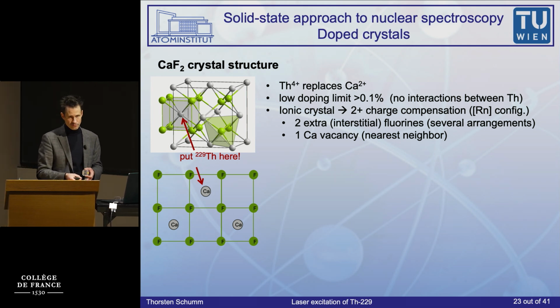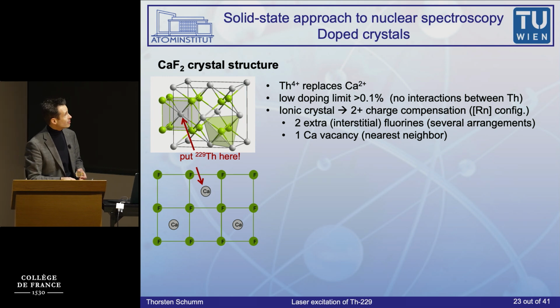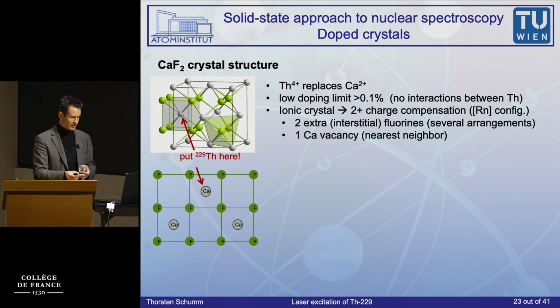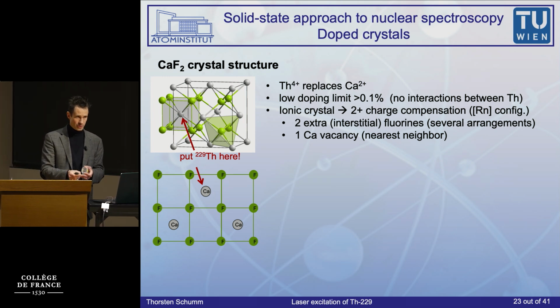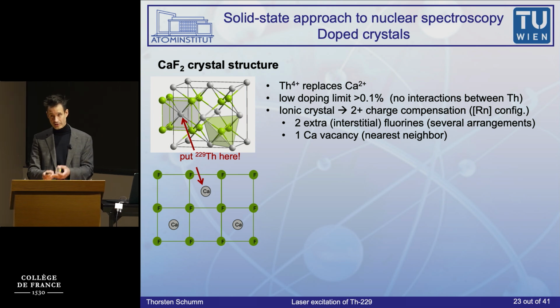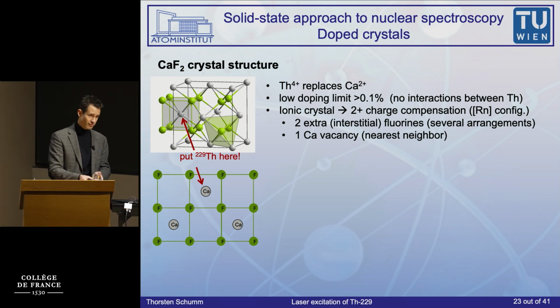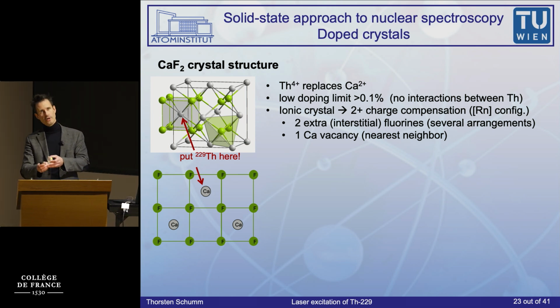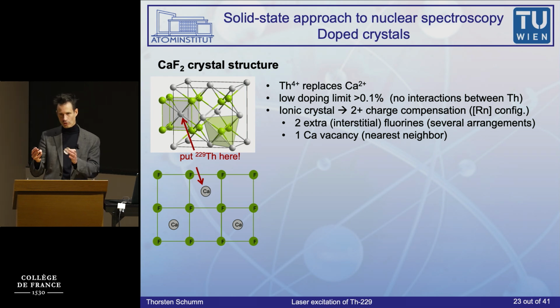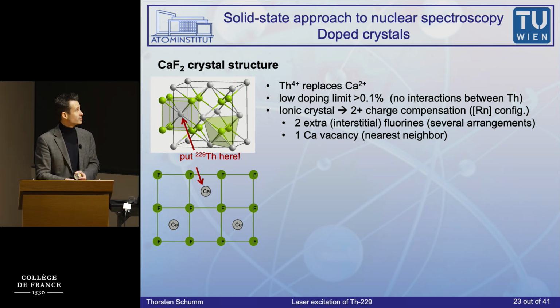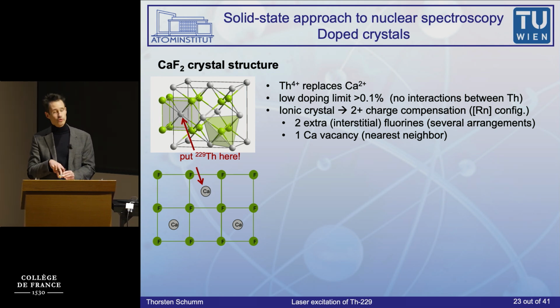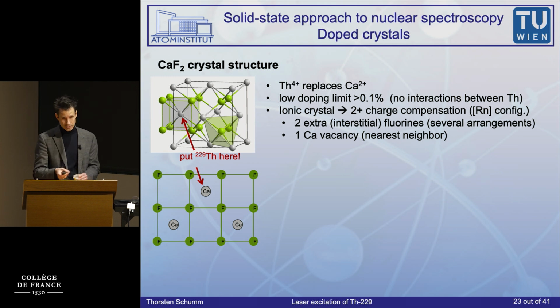And so there are very few materials which are actually transparent in this wavelength range, and the only choice there are are fluoride single crystals. There is magnesium fluoride, there's calcium fluoride, there is lithium aluminium strontium fluoride, but it always ends with fluoride. They are so-called ionic crystals, and it's the most transparent material we have. So that means that the task was to embed thorium-229 into calcium fluoride single crystals.